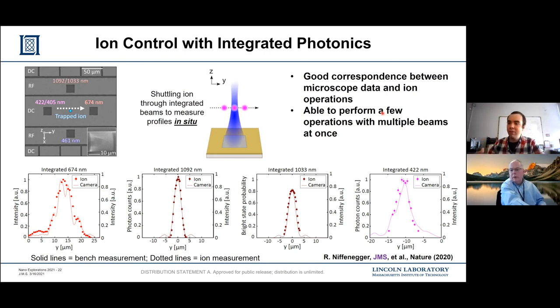And so we needed something relatively viscous. We also needed something that didn't outgas. At one point we were looking at a material that was more like a potting material, but we were afraid that it could increase the pressure in the chamber too much, particularly close up to the ion. Then just finding something that was fairly rigid as we cooled it down was the final thing, because those two requirements tend to push in the direction of something that's brittle. And so for that, we just had to increase the structural integrity of the whole package.